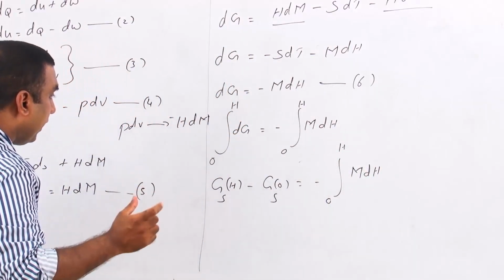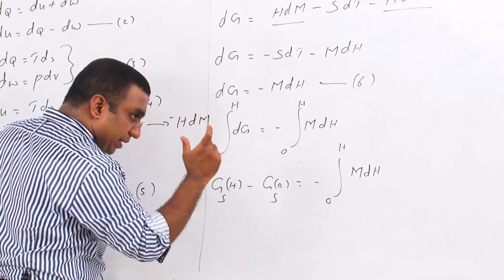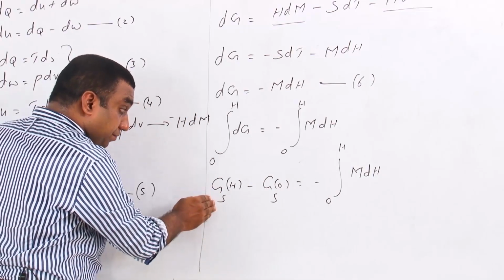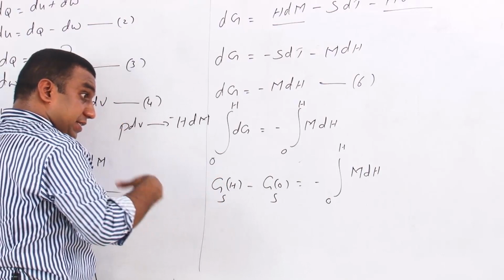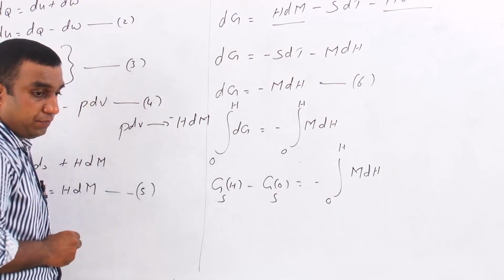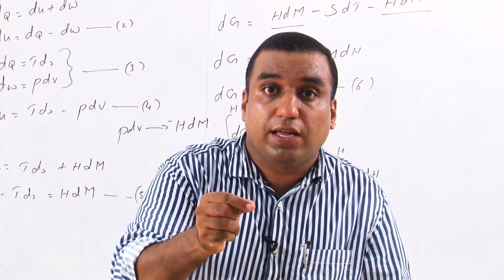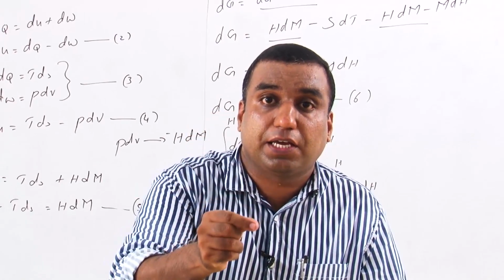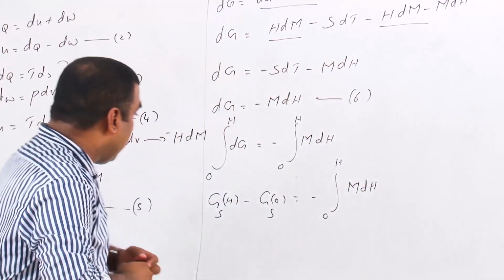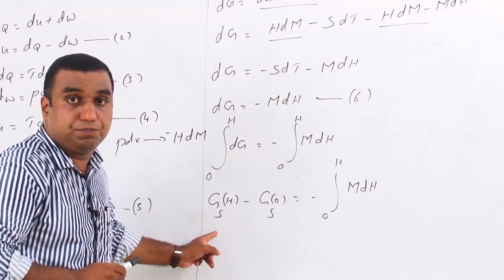This is actually the difference in Gibbs free energy of a material in the superconducting state when a magnetizing field is applied and in the absence of a magnetizing field. And this difference has a non-zero value only in the superconducting state. If we take the normal state, the difference in Gibbs free energy is 0.